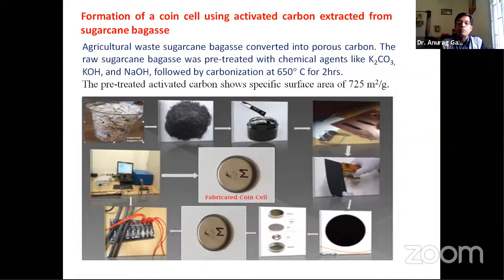Via that process, we bring it into porous carbon, because porosity is important for any material you want to use as an electrode in an energy storage device, either batteries or supercapacitors. You need a porous material, because the porosity is required so that the electrolyte ions can enter the pores, intercalate into the pores, remain for some time in these pores, and then come out for other oxidation-reduction reactions. So the material should be porous in nature, and it should have a high surface area, which is always required for energy storage device electrode materials.